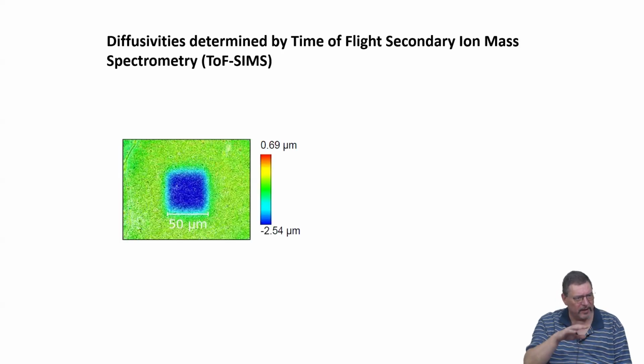So in real space we have a finely polished surface. We apply a non-radioactive tracer, like some isotope which is stable, but which is not as abundant in the natural isotope mixture as we apply it here. So normally we apply 100% enriched stable tracer, and in the alloy it might be that this isotope has a fraction of, I don't know, 10%, 5%, 15%. If it has more, then it's difficult to measure, because then your scatter will be larger, because your alloy will always contain some fraction of the stable isotope mixtures of all the isotopes.